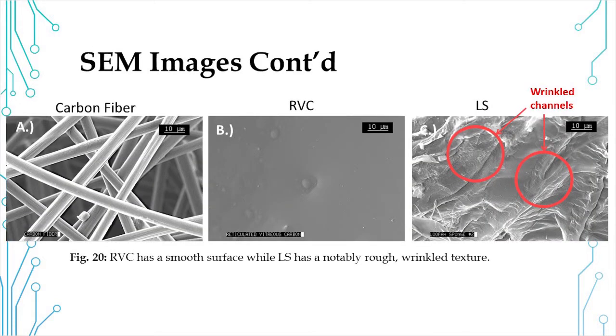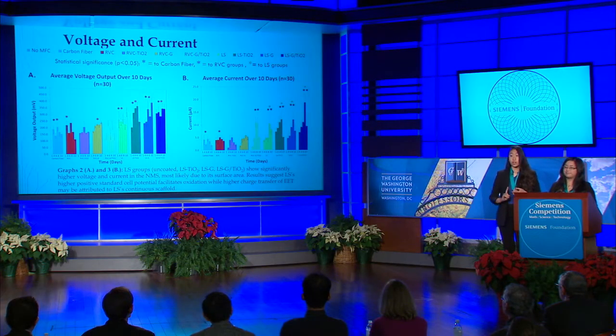RVC is a glassy carbon material and has a much smoother morphology compared to the loofah sponge, which has this very wrinkled texture. The wrinkled texture can be attributed to the pyrolysis process, in which the shrinking of the plant tissues causes very wrinkled channels to form. And these wrinkled channels increase the surface area, which may allow for more bacterial adhesion for a more effective MFC performance. For the electrical outputs for the natural marine sediment, we calculated the voltage, current, power, and power density.